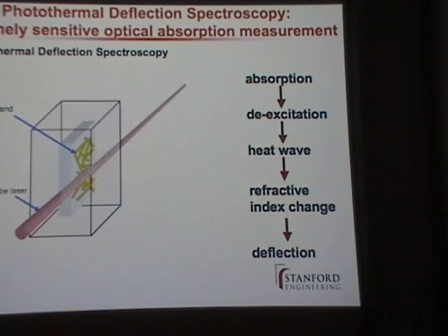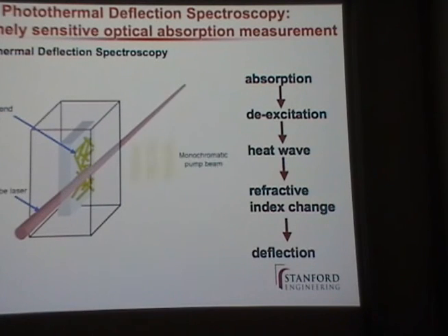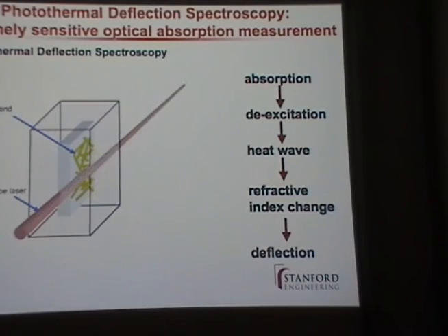There is another variation of this measurement, where rather than measuring the heat that comes out, you measure the photocurrent. It's called the constant photocurrent method. So in that case, it's easier to put an electric field. You put a bias, then you chop a small signal, and you might be able to measure that. So yeah, that would be an interesting experiment to try.